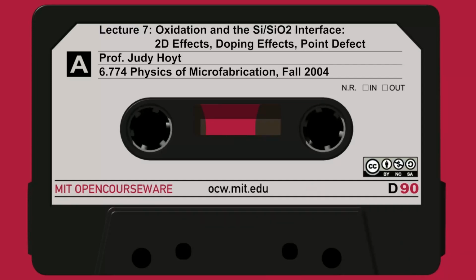People in fact not only found the thickness to be different, they extracted the B and the B over A parameters. So this is the oxidation rate, or these rate constants, B over A and B, as a function of boron concentration. I'm sorry, it's actually phosphorus doping in this reference. The B over A parameter is the one impacted. So above a certain concentration of dopant, here above about 10 to the 19th, B over A takes off. So it's going up quite rapidly.